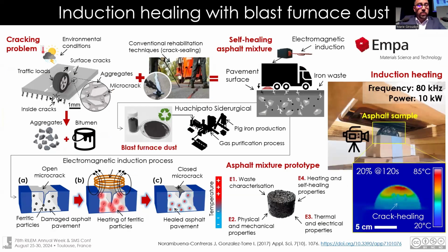And also it's possible to use blast furnace dust from the steel industry. This is a small powder with metallic properties that is very good. You can reach a very good distribution inside the asphalt mixture, and at the same time, it's possible to heal the samples up to 100%.